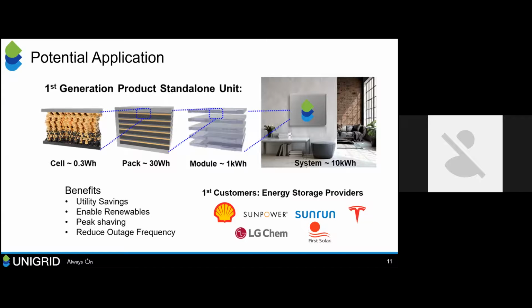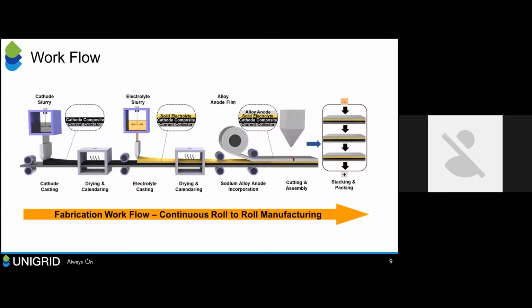But the thing is, considering none of the electrolyte really satisfy the thermodynamic energy diagram of the decomposition, the electrolyte decomposes, right? So even if it heats up, it's an uncontrollable heat. And if it heats up to more than 100, 120, 130 or 140, maybe you're getting the high capacity, right? Because of the fast kinetics, but your degradation of the battery in the solid state should be also higher, right? So do you need a more complicated battery management system? Because it helps to the high value, but conceptually it should degrade your battery also very fast. So can it really totally get rid of the management system, or what's your perspective on that part?